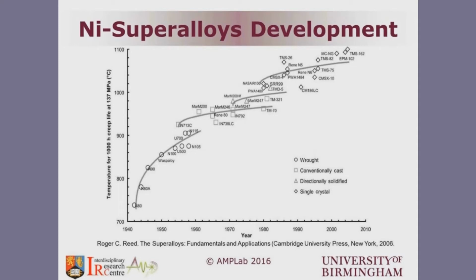As a matter of fact, that resulted in us adding more alloying additions of elements like aluminium and titanium, which can strengthen the material by the formation of the gamma prime phase. We also added some other elements like cobalt and chromium to increase the higher temperature oxidation capability and also the control of the phases that are present, like the carbides, within nickel superalloys.